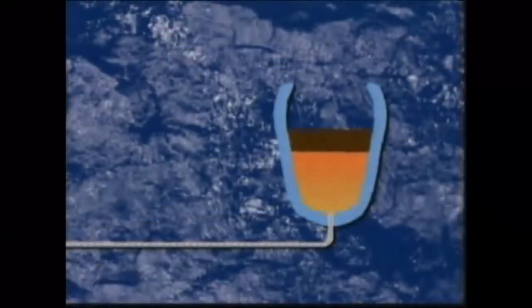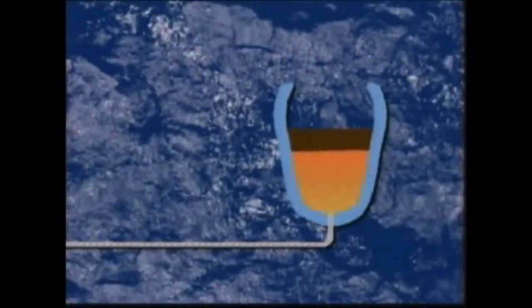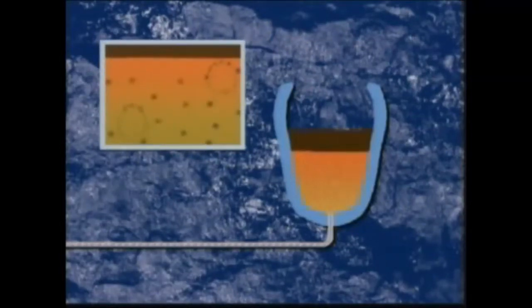The liquid steel is then stirred using an inert gas, argon. This is to ensure composition and temperature to be homogeneous throughout the ladle. In addition, the gas bubbles float out impurities, which are absorbed into the slag.